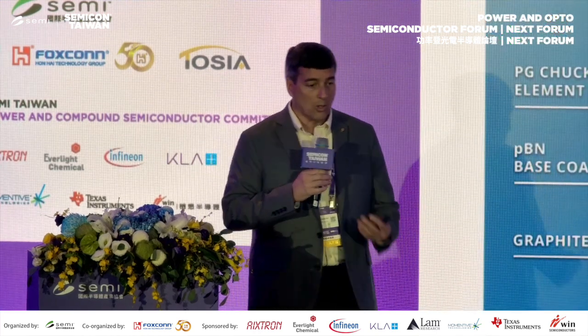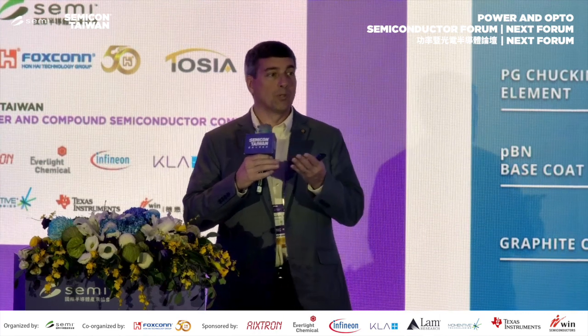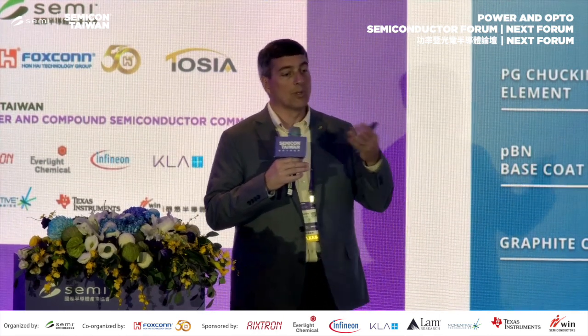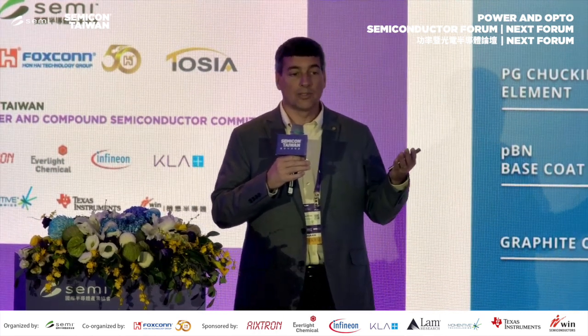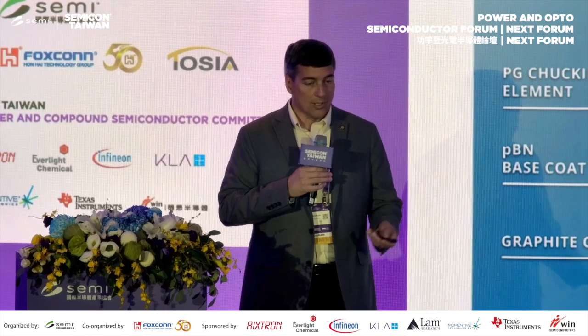So how do we really use this to our advantage in a heater? We start with a graphite core, and then we'll put on a PBN base coat, right, which is nothing more than an insulating layer. Then we'll put on a series of pyrolytic graphite layers on the top and on the bottom. On the bottom, we'll put the heating element, and on the top, we'll put the chucking elements, right? And then we'll cap all of that with an additional PBN layer, all right?